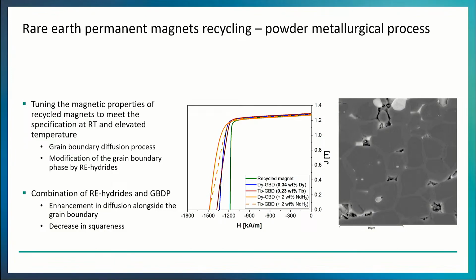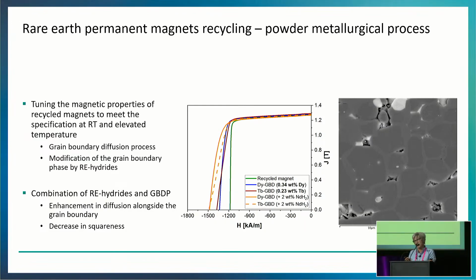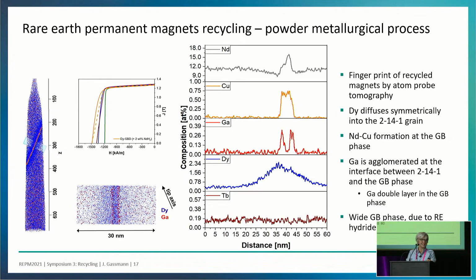Then you also have the way of tuning the magnetic properties according to the application of these recycled magnets. You have to govern these grain boundary diffusion processes during the production, and you have to have a good modification of the grain boundary phase by the addition of rare earth hydrides. This combination and these grain boundary diffusion processes bring us the good properties of the permanent magnets. Somehow we lost this knowledge a little bit because all the permanent magnets are produced in China at the moment. So we also have to learn how to do this in a proper way, at least in Germany again.